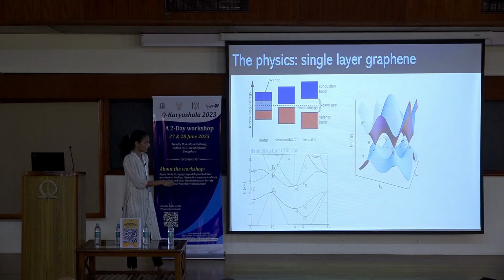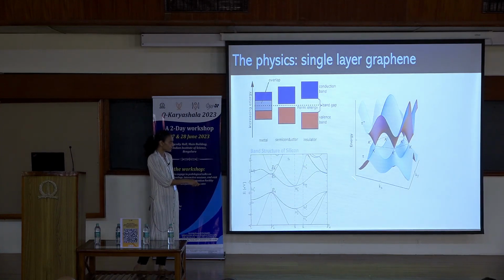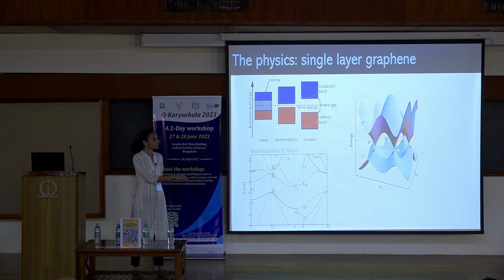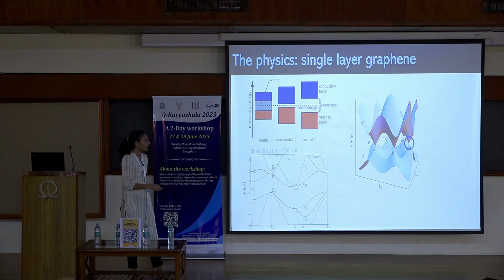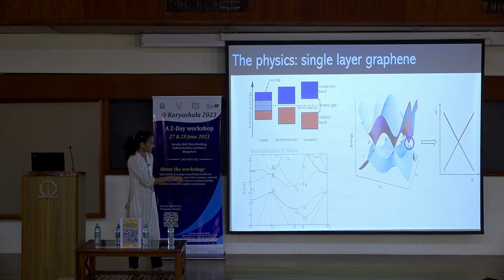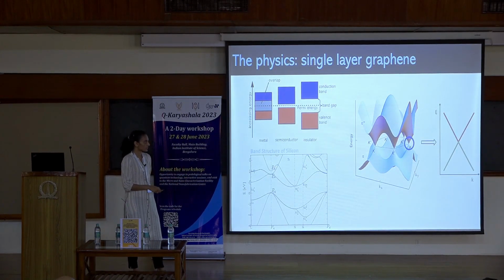In case of graphene, if you plot energy versus K, this is now plotted as Kx, Ky, you see that the band structure where your Fermi level is, that's linear. Okay, so that's the main distinction that you can easily draw between silicon and graphene. And if you zoom in there, it basically looks like this, right? Instead of this parabolic shape, you have a linear dispersion in E versus K. That's the conduction band, and this is a valence band, and they touch each other. So there's no band gap as such, they touch each other.